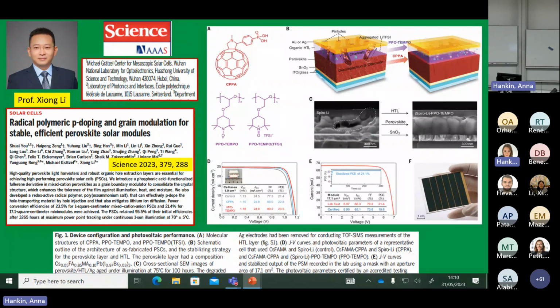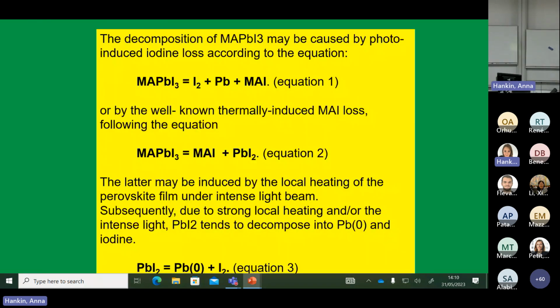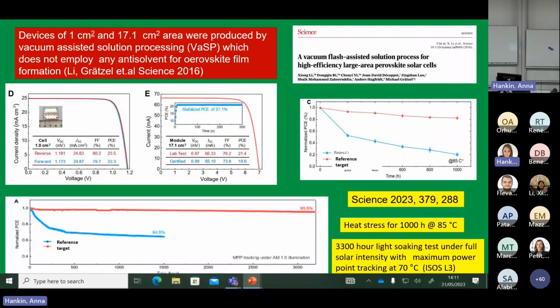We investigated a C60 derivative as a material that would sit on the grain boundaries, improve cohesion of the grains, and enhance electron flow across the grain boundaries. We also did a doping of the spiro with a redox-active polymer, a TEMPO derivative. And out comes a cell that, let me see, the module is more efficient. The module is over 21%, and the single 1 square centimeter cell, over 23%. That's very good. We are very happy about that. Now the stability of this, I'll show you as a final slide. I'll show you the stability, and then a few minutes about applications.